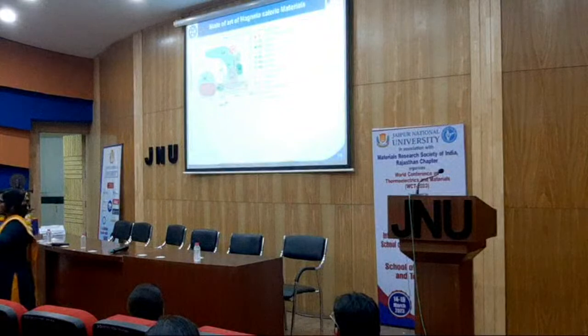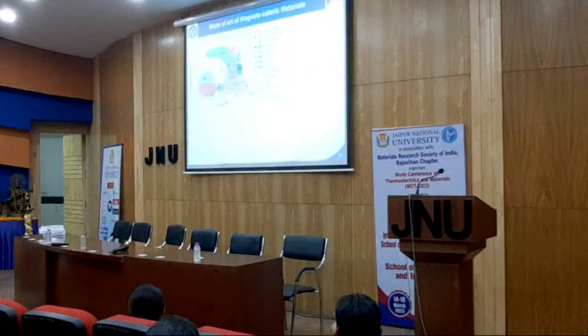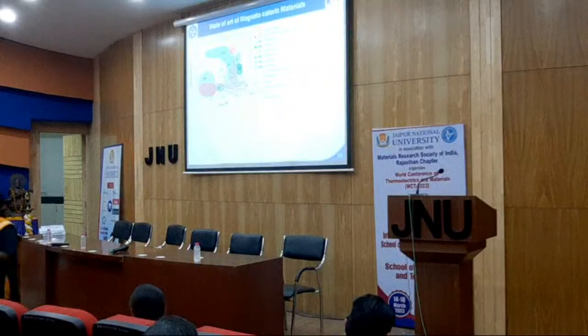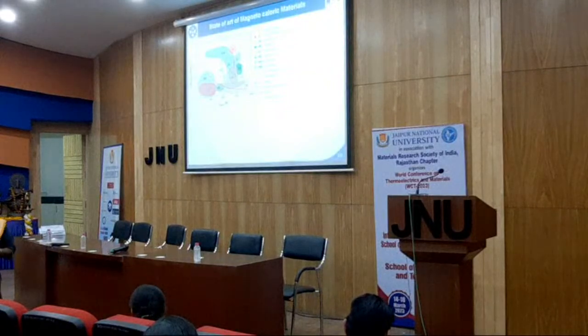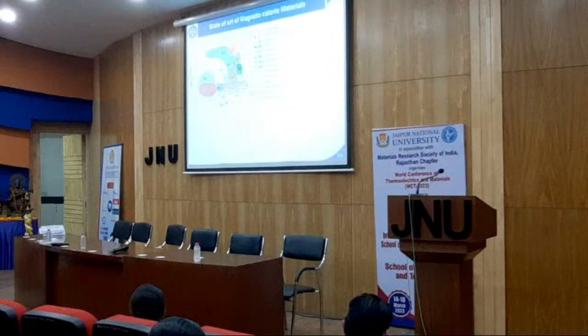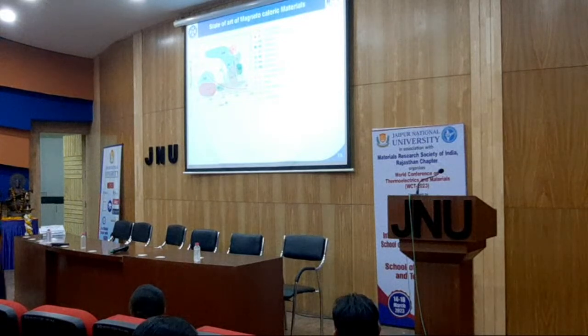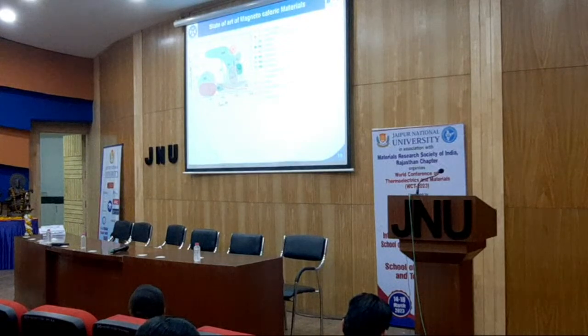Now I am just telling about the state of the art of existing materials which can show the magnetocaloric effect. There are around 12 families of compounds listed here, which show magnetic entropy change around 40 Kelvin, in different temperature ranges. But out of that, you must have seen that almost all the materials are based on intermetallics. There is only one family of compounds which is oxide-based.